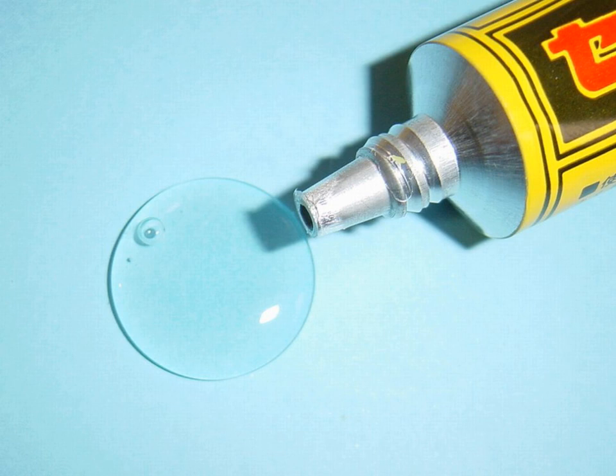Fracture can also occur in the adherent if the adhesive is tougher than the adherent. In this case, the adhesive remains intact and is still bonded to one substrate and remnants of the other. For example, when one removes a price label, the adhesive usually remains on the label and the surface. This is cohesive failure. If, however, a layer of paper remains stuck to the surface, the adhesive has not failed. Another example is when someone tries to pull apart Oreo cookies and all the filling remains on one side. This is an adhesive failure, rather than a cohesive failure.